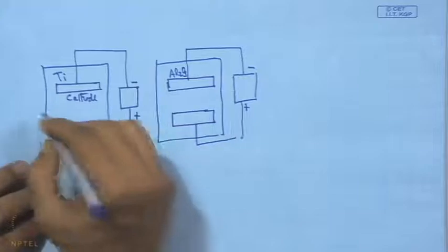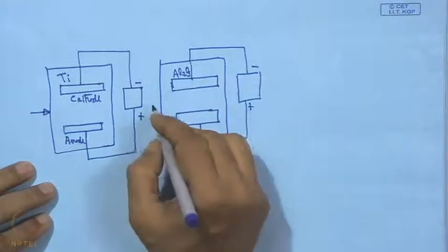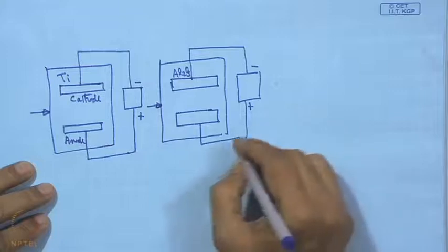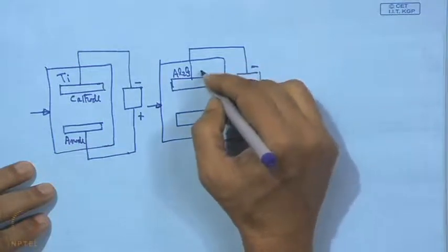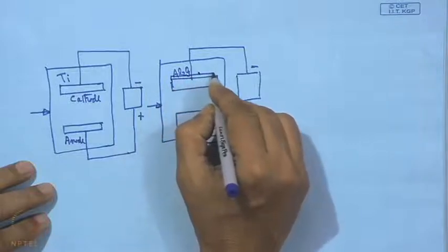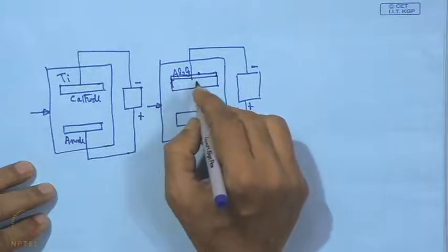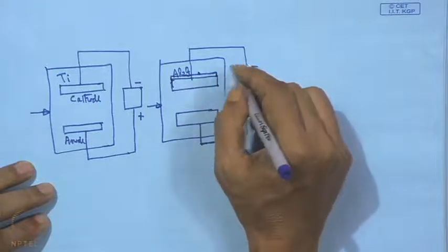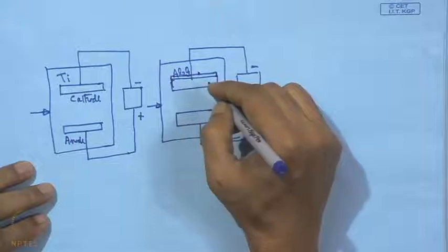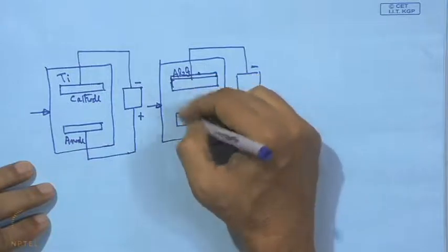Now, in this case, we have all the required features of sputtering. However, one thing that is missing here is the conductivity of this material. So, what is going to happen is that this will be polarized and there will be accumulation of charge, with no conducting path. Though we have a cathode plate just behind it, on top of it we have a target material which is a non-conductor. So, there will be accumulation of charge, and it will ultimately lead to heating of the target, and it can even lead to arc discharge, which is the most undesirable thing in this whole sputtering process.